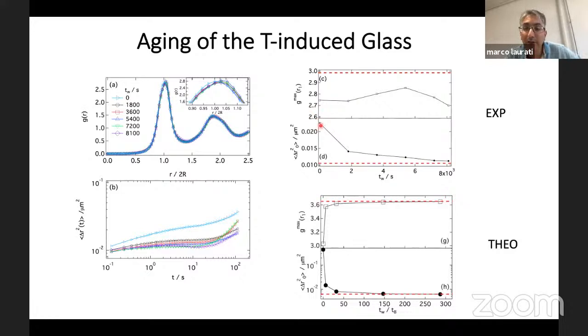So as you see, the dynamics of the system, so these red lines are essentially the values of the glass obtained through the concentration route. And as you can see, the dynamics effectively evolve in the experiments toward the same dynamics of the glass obtained in the other route. But the structure doesn't evolve, essentially. It remains, well, maybe there is this peak, but definitely it doesn't go to the structure of the other route.